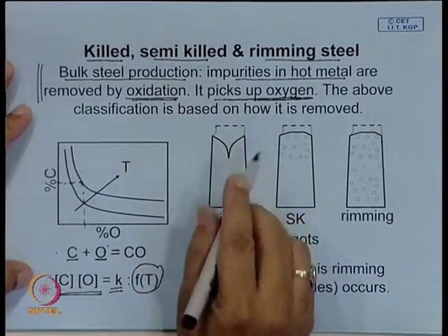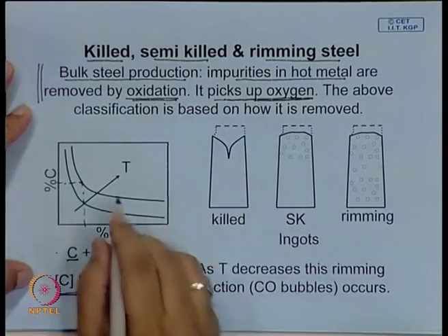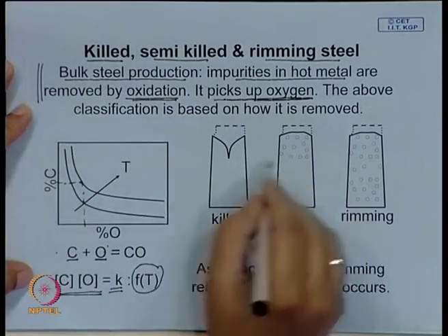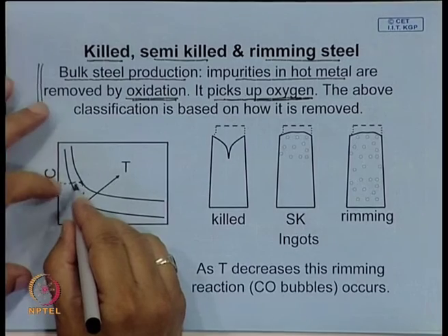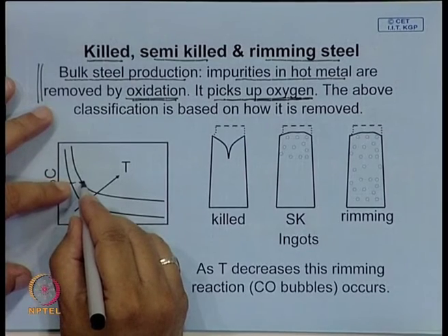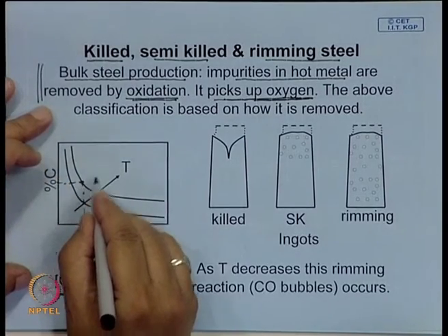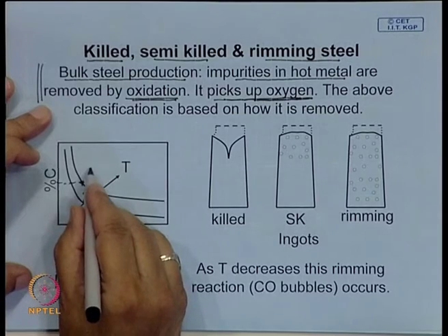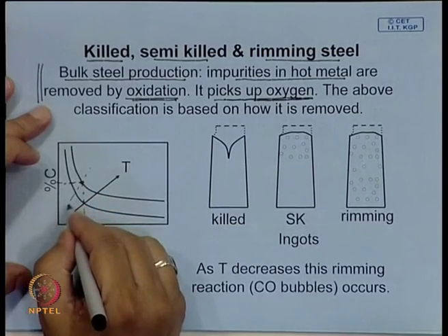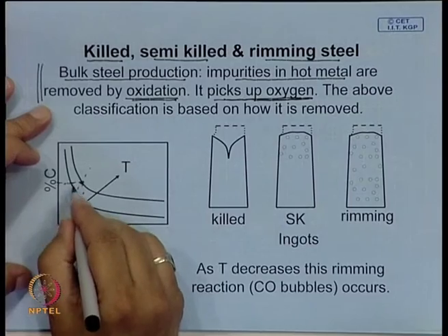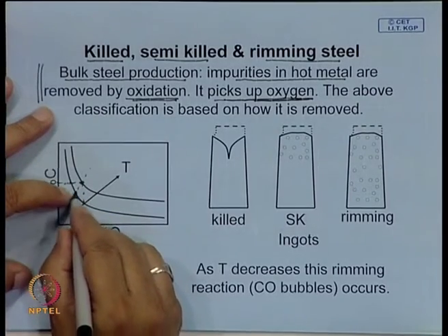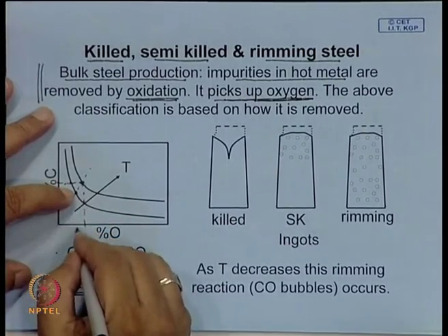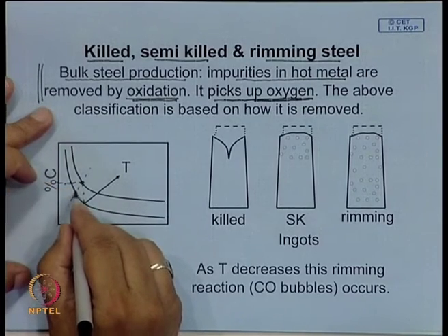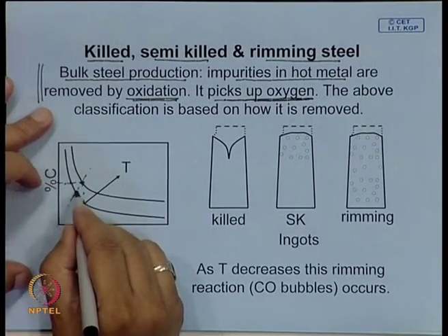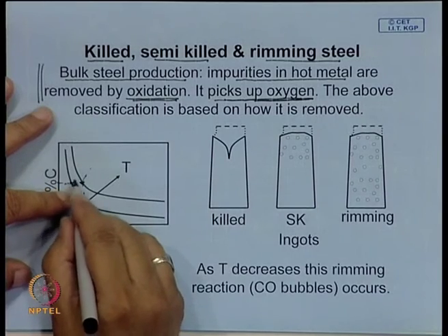But when you cool the steel, when you pour the molten metal into an ingot like this, what will happen as the temperature goes down? It has a higher amount of carbon than the solubility allows, and that carbon has to now come down. So, carbon will come down along some line. If carbon comes down, oxygen also will come down, as the solubility of oxygen also decreases. So, what happens to that excess carbon?